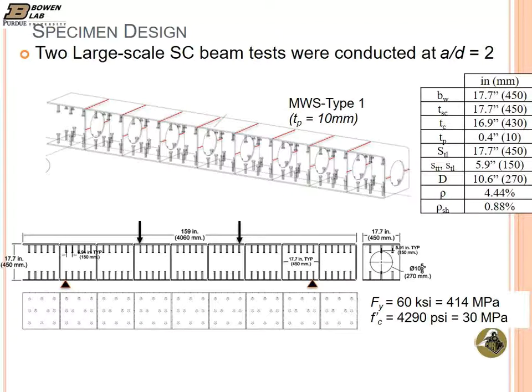This is the first specimen, which we call MWS Type 1. For this specimen, we had the inner plates transverse to the length, and some of the basic dimensions are given in the table on the right. We had a width and thickness equal to 450 millimeters. We had a steel faceplate thickness, which is also the inner plate thickness, of 10 millimeters. Inner plate spacing was 450, stud spacing was 150, the diameter of the inner plate hole was 270, and that equated to a total reinforcement ratio of 4.44%, and a shear reinforcement ratio of 0.88%.